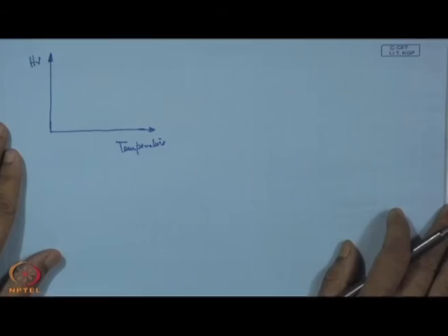However, what one can see is that if the coating is porous and having voids, imperfection, in that case the indenter can have an easy penetration, indicating less hardness. So, what is understandable is that when we have a finer grain, finer grain means obviously a denser structure. With the same volume, if we have larger grain and if we have finer grain, obviously with a finer grain we get a densified structure, which is much more compact in nature. So, with this compact structure one would expect an increase in hardness. As a corollary we can say that if we increase the temperature, the hardness of the coating is also increasing.